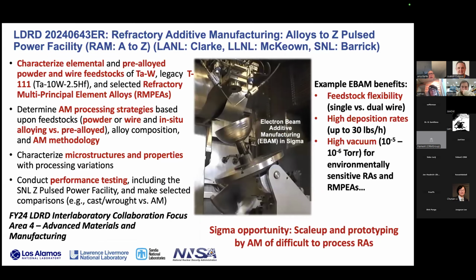So on the refractory alloy space at the lab, we actually have an ongoing project right now that involves not only Los Alamos, but also Livermore and Sandia as well, looking at refractory additive manufacturing. And this really has a feedstock angle to it. We know that having feedstocks of refractory alloys, especially novel alloys, is really challenging and quite expensive. And so the questions we have kind of surround what happens if we use pre-alloyed powders or wires as compared to doing the alloying in situ with DED kinds of processing.